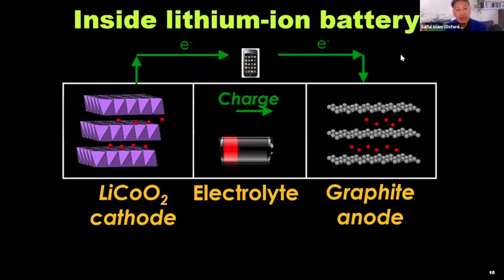And in between the two bread slices, between the two electrodes, is a good sandwich filling. The meat, or cheese if you're vegetarian, and that is a very good lithium-ion conductor. In this case, a lithium salt with an organic solvent, and that allows lithium ions to move very quickly between the two electrodes. So when you're charging your phone tonight, you're seeing chemistry in action. Lithiums are moving from one electrode to the other.